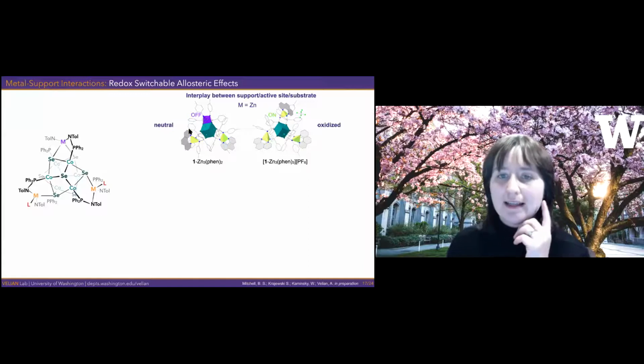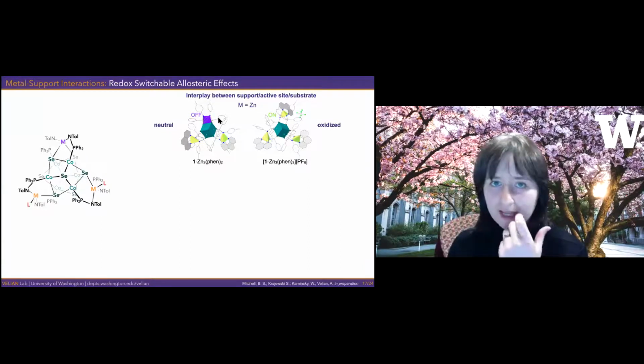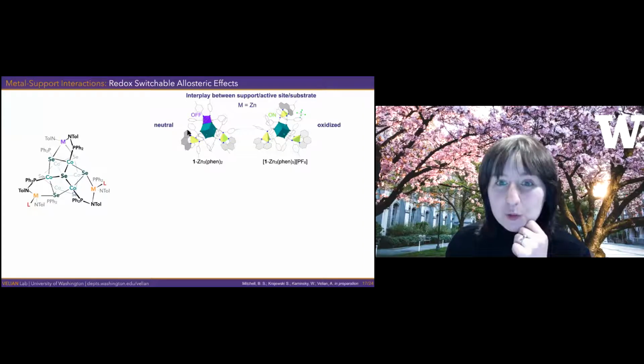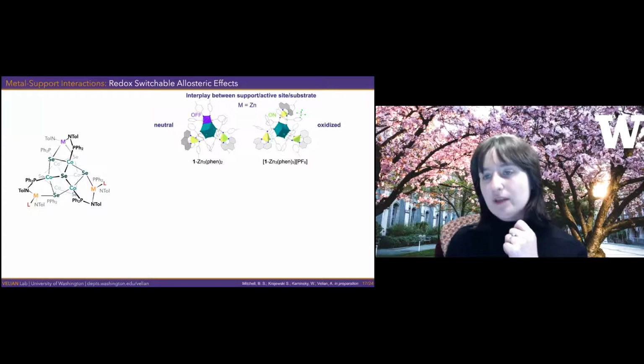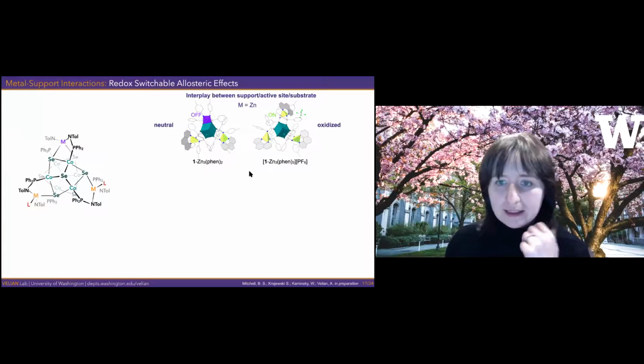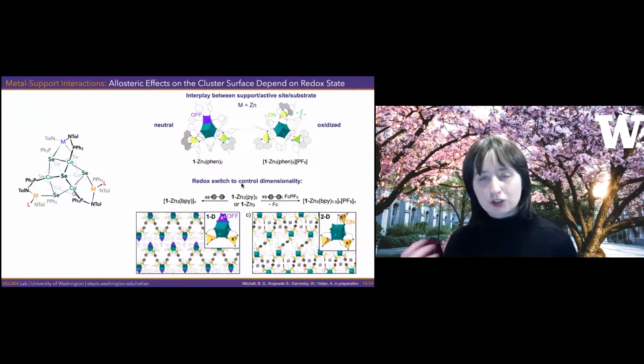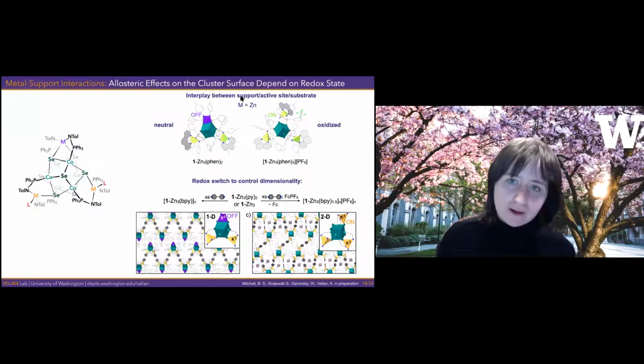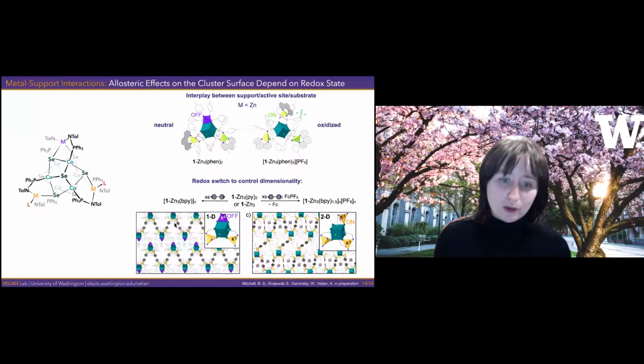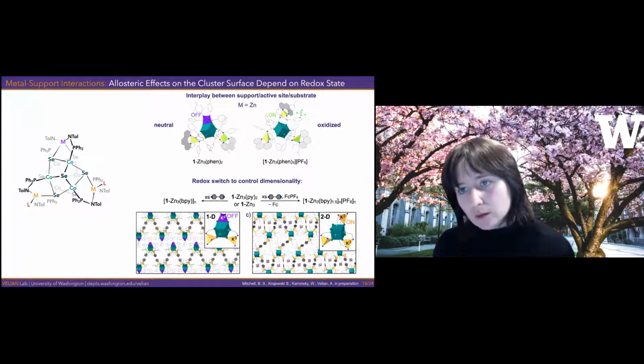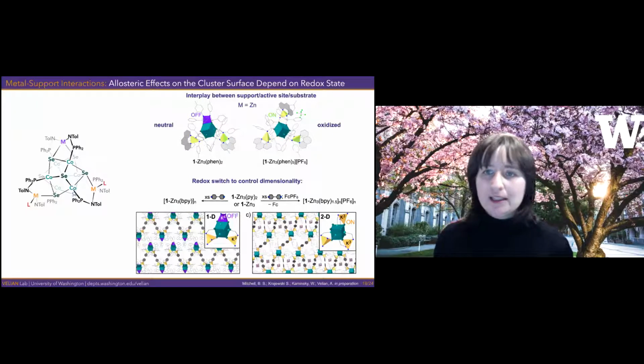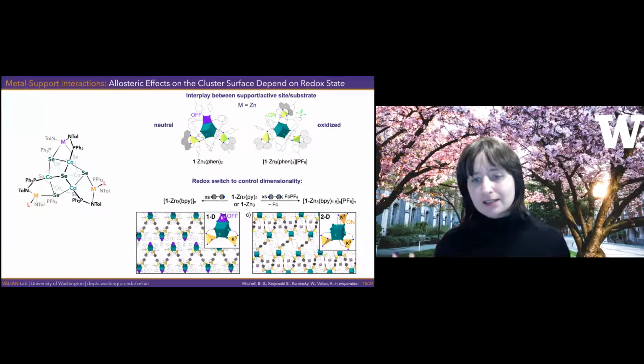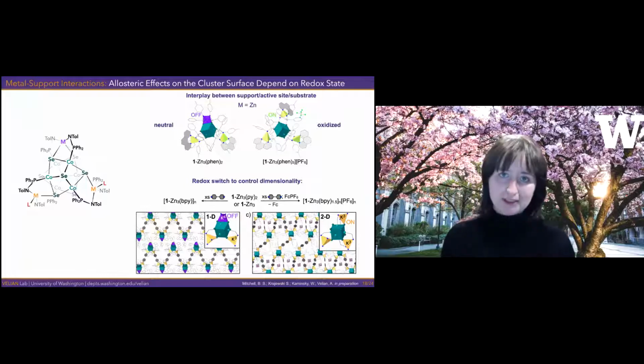But what was really cool is that now, not only do we have the site differentiation of the edge sites, but if you oxidize these, you turn on this site and now it can engage with external ligands. One way that we can put this to work is to show that we can actually control the dimensionality of assembled materials. If we start off with this as a building block, we can make a wire. And we do. This is again from single crystal X-ray diffraction in its off state. But now if we oxidize it, we give rise to the formation of two-dimensional nanosheets. And so here it is, this sort of redox switch enabling us to control the dimensionality of atomically precise materials. And I'll loop back to this idea in just a little bit.